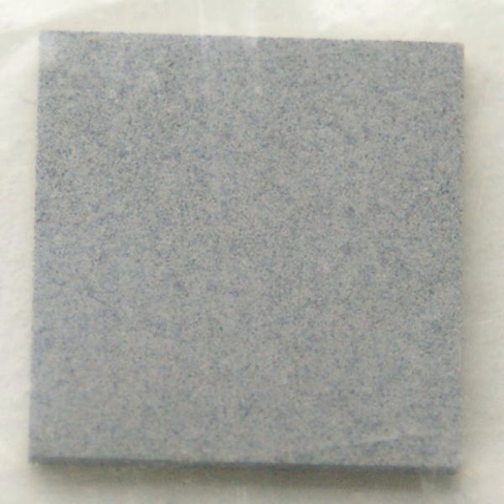The use of silicon nitride cutting tools has had a dramatic effect on manufacturing output. For example, face milling of gray cast iron with silicon nitride inserts doubled the cutting speed, increased tool life from 1 part to 6 parts per edge, and reduced the average cost of inserts by 50%, as compared to traditional tungsten carbide tools.